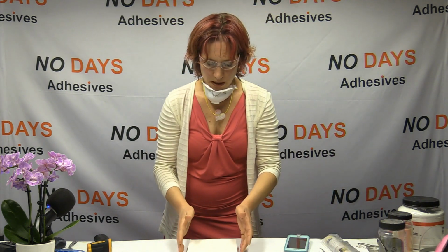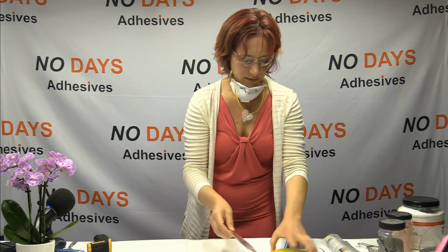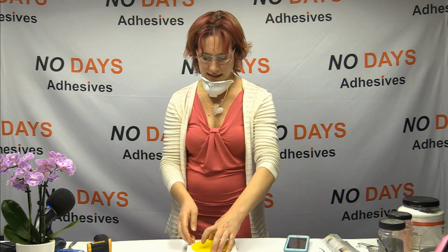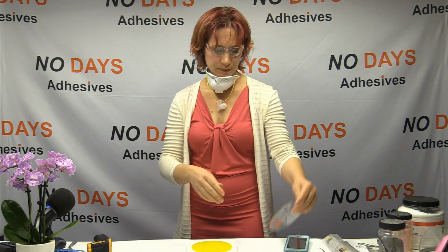So we're gonna anticipate that, and we're gonna put some powder down first. So I'm gonna take my piece of glass. A piece of glass goes down on my board. Now this I could do directly on my ceramic shelf as well, but if I'm having volume control issues, there is a chance that I'll get a big bubble that raises up. Chances are smaller since it's a small piece, but if this were a big piece, there's a greater chance for the edges to seal against the kiln shelf, and then the air gets trapped and goes where it can, which is up and out, right, at higher temperatures.